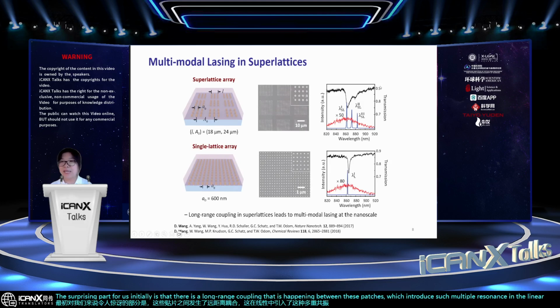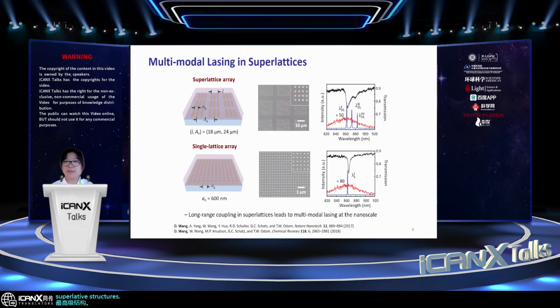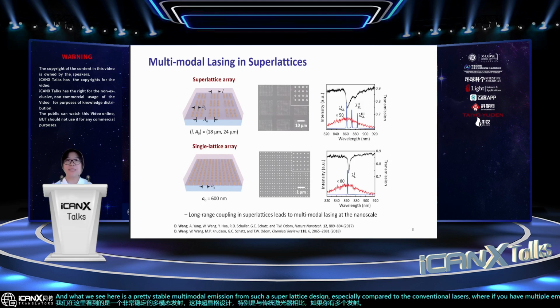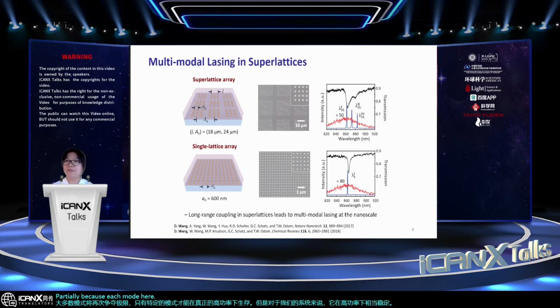And in the case of lasing, we use dye molecules as a gain medium and achieve multimode lasing from such superlattice structures. What we see here is a pretty stable multimodal emission from such a superlattice design, especially compared to conventional lasers, where if you have multiple laser emissions, most of the modes will compete for limited gain, and only a specific mode will survive at a really high power. But our system is pretty stable at high powers, partially because each mode has distinct near fields. So the competition for the gain is minimized in such a multimodal laser system.